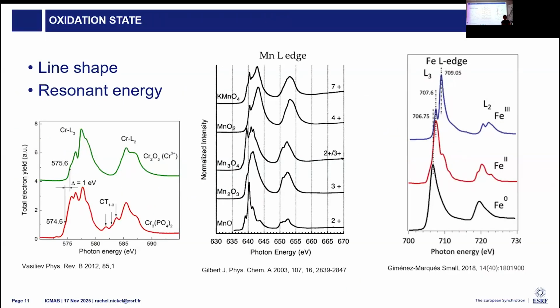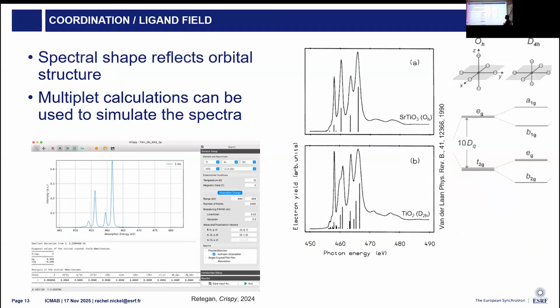So common things that we're looking at with absorption experiments is oxidation state. You can tell the oxidation state of a specific element based off of either the line shape or shifts in the resonant energy. It gives you information about how these atoms are bound. We can also get detailed information about the coordination and ligand field. So here I've shown an example where we have splitting from an octahedral structure with 2 discrete energy levels to a distorted structure where now we have 4. And the complexity of the measured XAS signal scales accordingly.